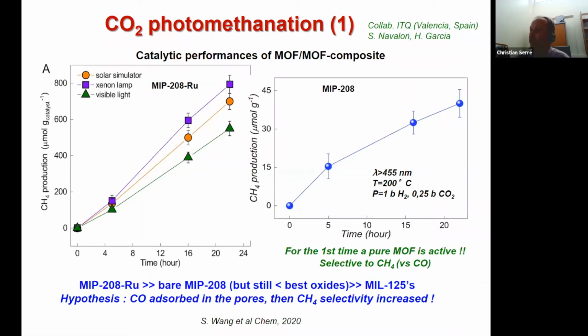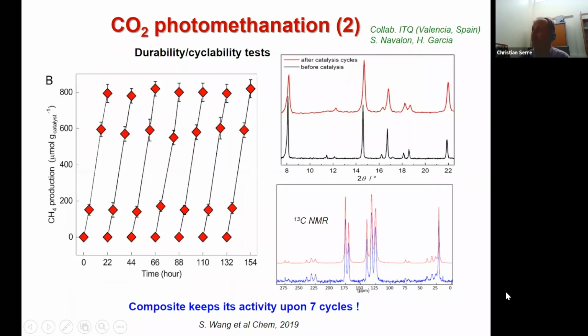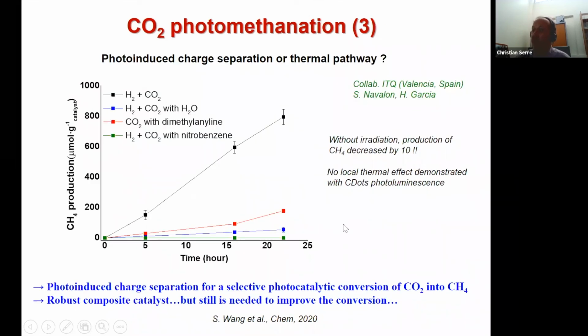And also one interesting hypothesis is, because you have a porous solid here, the MOF is porous, that the selectivity is something very important in CO2 reduction. You want to reduce CO2 and to produce methane, but you don't want a side product like CO. And the hypothesis is that CO was adsorbed in the pores, which enhanced the selectivity towards methane. The material was stable during 7 consecutive cycles and with no evidence of degradation by XRD or by solid-state NMR on the ligand after 7 cycles. So this is very important. And to better understand the mechanism, they did some additional experiments.